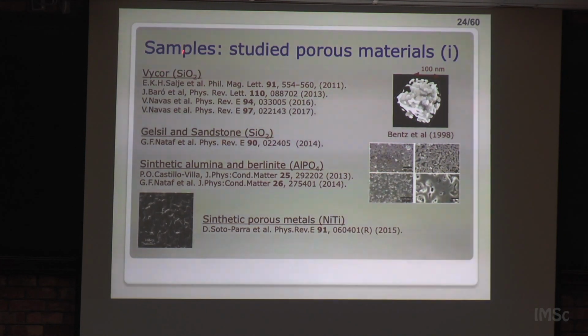Gelsil is a similar one. It's also SiO2. It's also synthetic, but it's made from grains of quartz that are sintered. So it's a different way. This also gives very good results, similar to Vycor, not as good, but similar. Then we also compared with sandstone, which is a similar material but natural. It's just sand that has been compressed by geological history. We have also studied other synthetic materials, alumina, berlinite, even metals, many more.